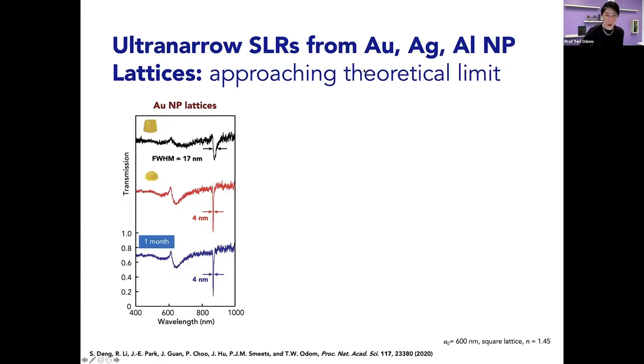So if we evaluate the properties, we now start to get very narrow resonances that start to approach the theoretical limit. For these as fabricated particles, the full width at half max is not very impressive. And then in the annealed case, not only does the localized plasmon look nicer, but we have a reduction to 4 nanometers. And then after a month, it's also still very narrow.